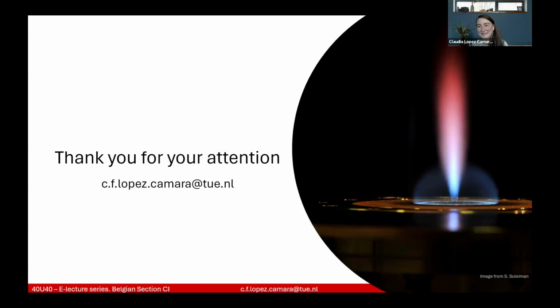Yeah, so yes, thank you for that question. It is a fair question indeed, because it could have been happening, but that's not actually what we would expect. The temperatures are really different from the ones that we use in the oven than the ones that the graphene sees when it's far; temperatures are really high at the plasma region, but of course they decay as they move farther from the plasma region. So we do not expect graphene to be burned.